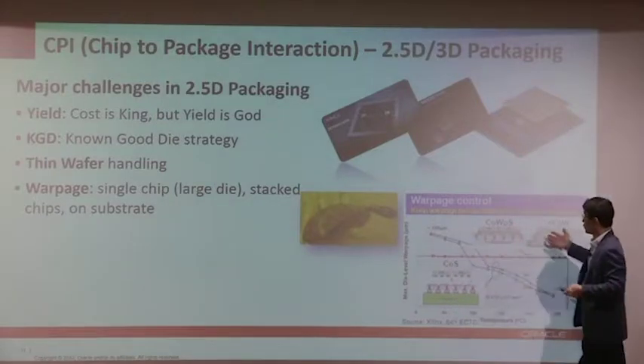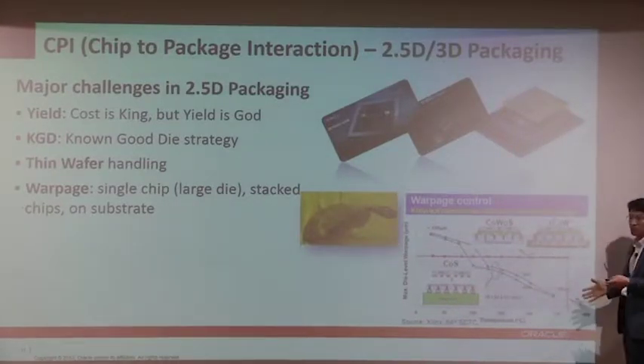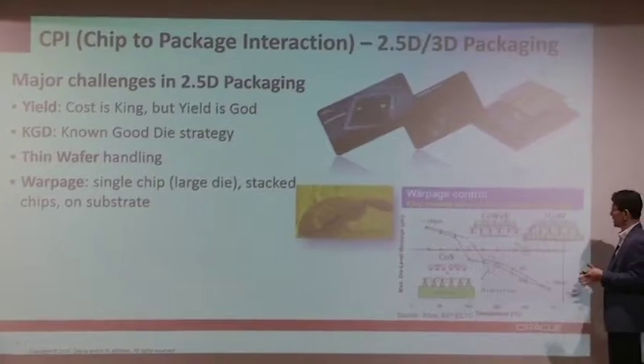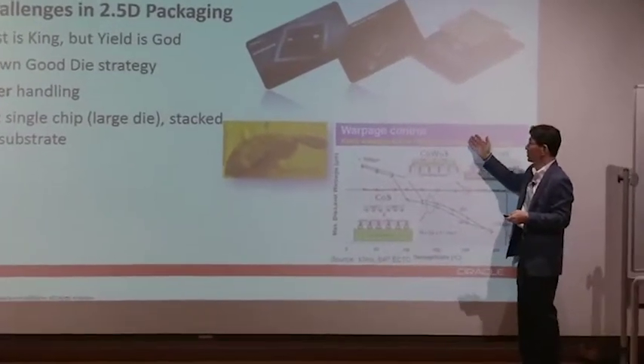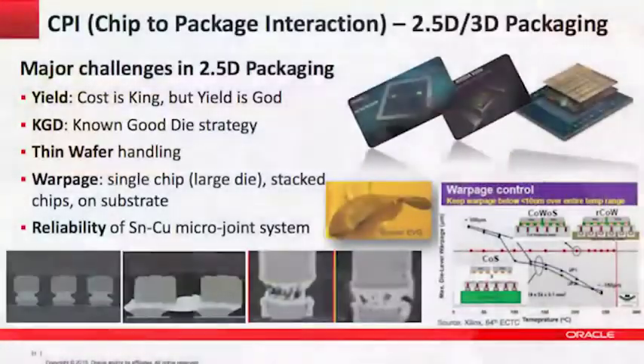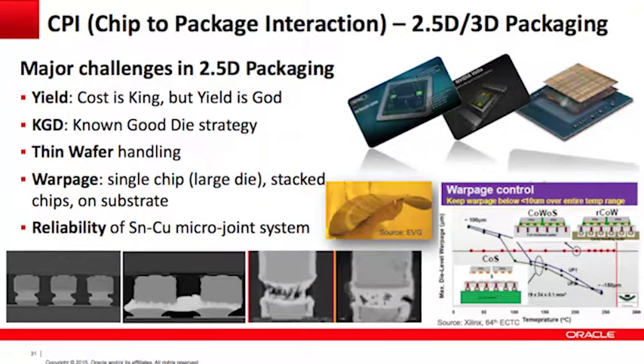And the warpage change is very important, anytime, any place. And this warpage control should be within some range, through the entire temperature range, from room temperature to cold temperature and high temperature over 200 degrees C. We need to have it below 10 micron warpage. Otherwise, it's going to create failure in the integration of the package.